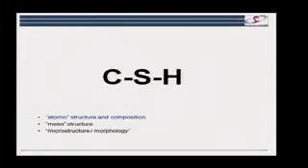The other thing is this calcium silicate hydrate. Here we can see what it looks like on a fracture surface in the scanning electron microscope. And we're going to come back and look at this in a lot more detail. Now, you'll read most places that it's amorphous. I think nowadays most people will agree that that's not really well expressing the state of things. I think it's much more correct to say that it's nanocrystalline because it does have a very definite structure on the atomistic level.